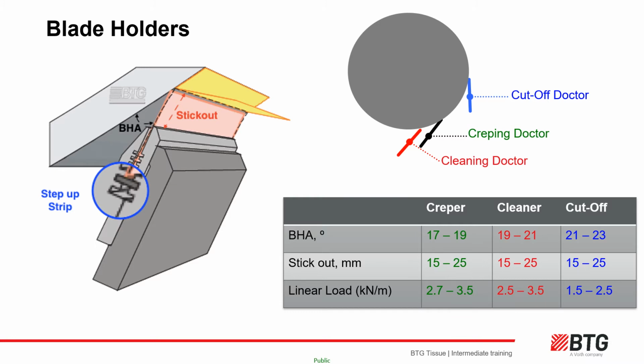Blade holders often have a series of manual relief or load nuts on the front and back edges to enable edge issues to be assisted by relieving or increasing load locally at these edges. It is, however, not the pressure which is critical measure on a blade holder. This would be the linear load across the blade measured in PLI, kilonewtons per metre or newtons per millimetre, which must be converted from pressure in bar, pounds per square inch or kilopascals. Each blade holder will have its own conversion chart which can be made by taking several measurements of the holder and converting it to a loading curve.